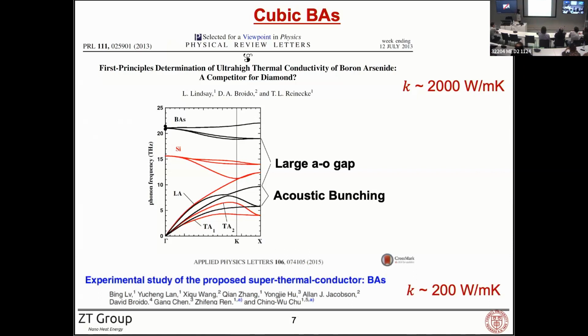But 2 years later, the experimental work showed only 200 watt per meter Kelvin, which is 1 order of magnitude lower. This large discrepancy begs the question: was the calculation inaccurate, or was the sample not pure enough, so it contains defects causing extrinsic scattering mechanisms lowering the thermal conductivity?